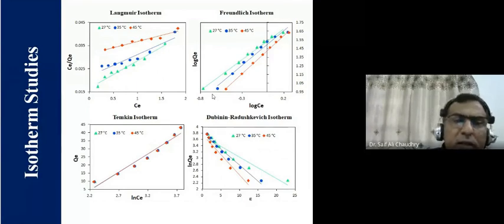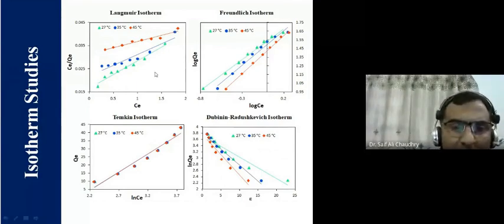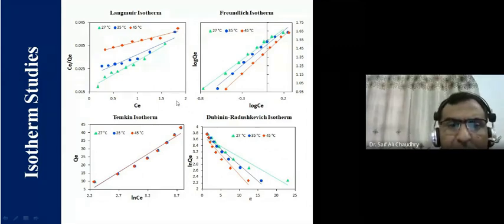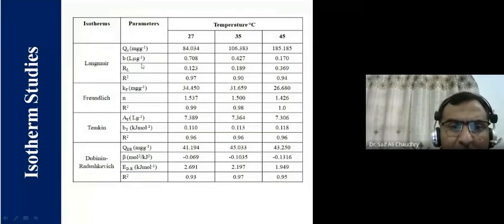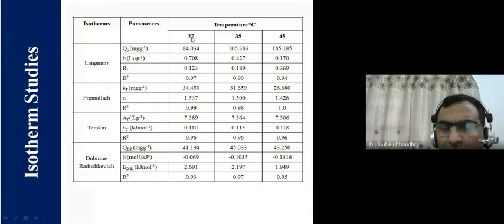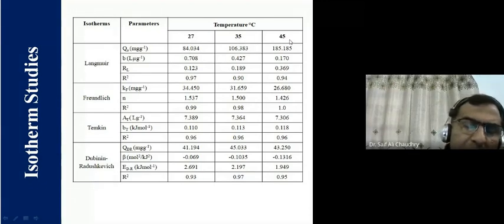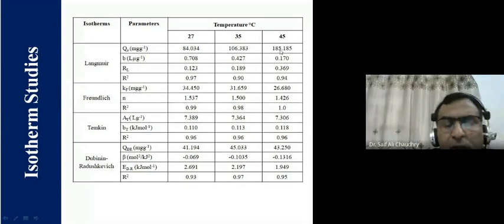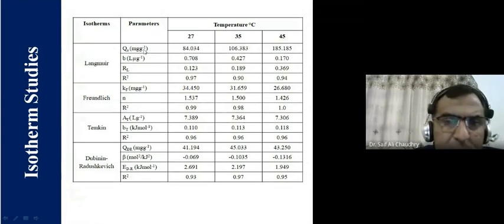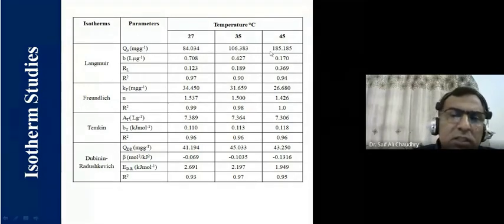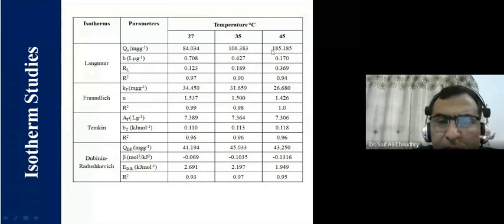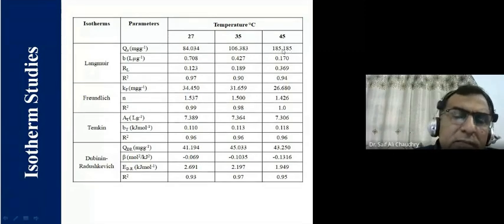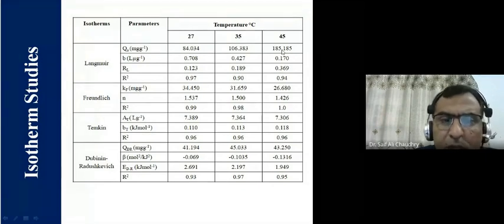Actually, this is the Langmuir isotherm. Freundlich isotherm has been applied, Temkin isotherm and Dubinin isotherm, and these isotherms give us these parameters. This Q naught value is important. It is 84 at 27 degrees, at 35 degrees Celsius it is 106, and at 45 degrees it is 185. This indicates that the adsorption capacity of the material increased with increasing temperature. So therefore, 185 is a very good number. Therefore, the material was good in that sense.